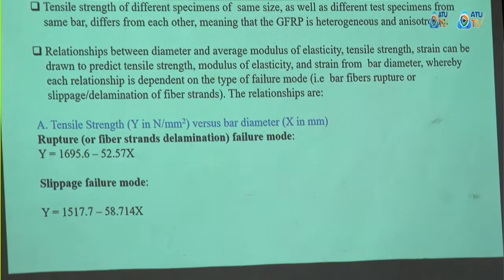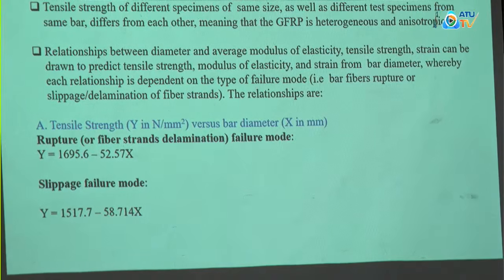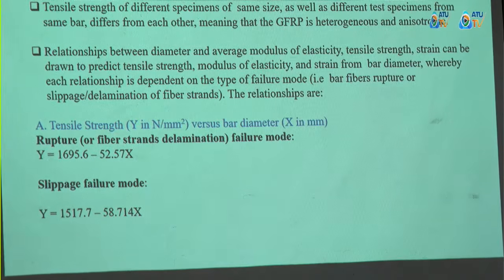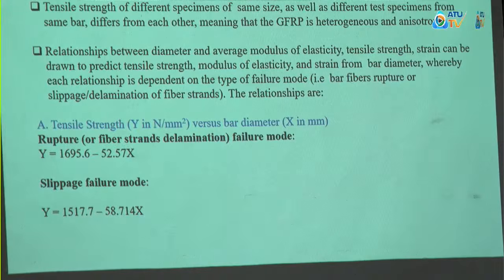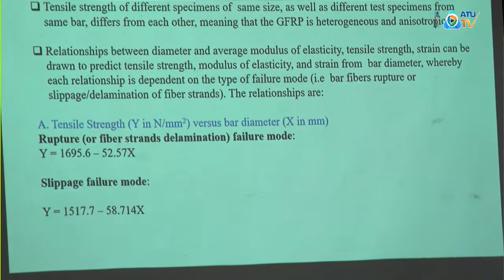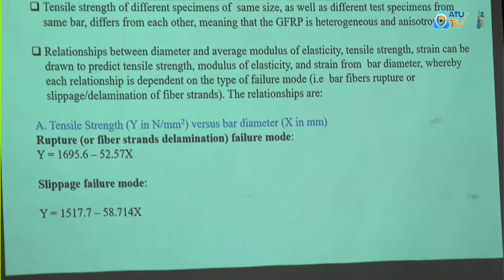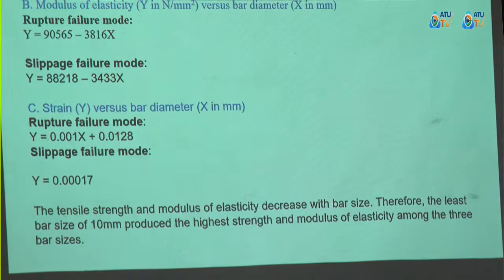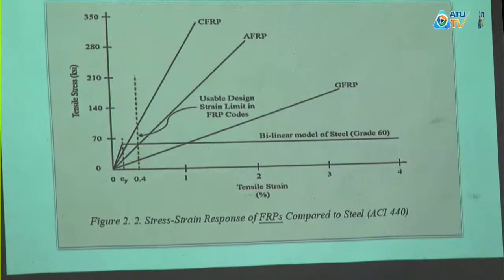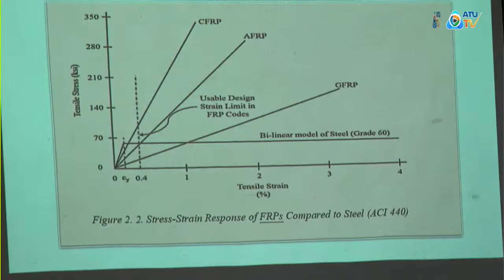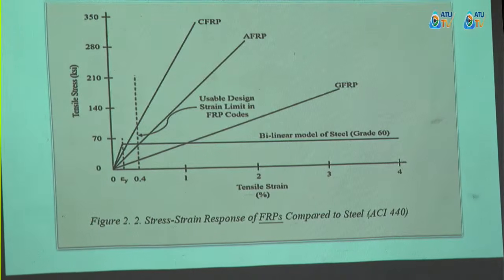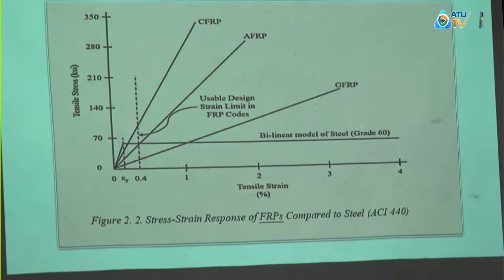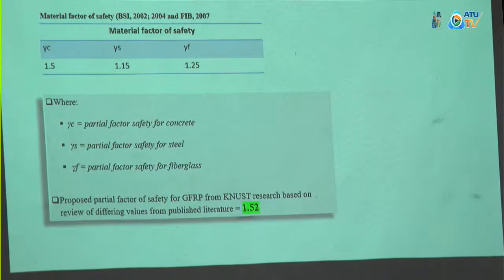Okay. So the tensile strength of different specimens of the same size, as well as different test specimens from the same bar, differs from each other, meaning that the GFRP is heterogeneous and anisotropic. There is an equation for the rupture mode and the slippage failure mode. This graph gives us a comparison of the FRPs as compared to steel.